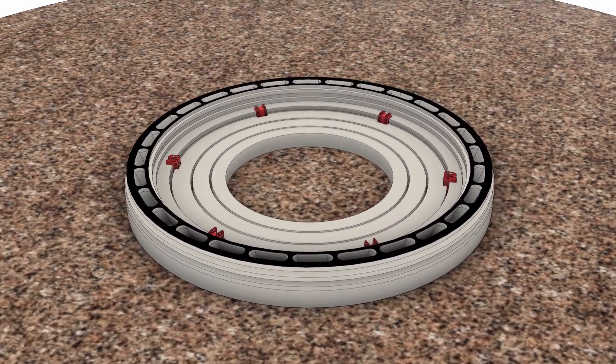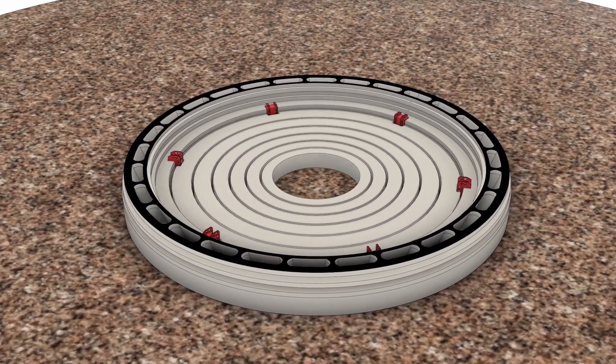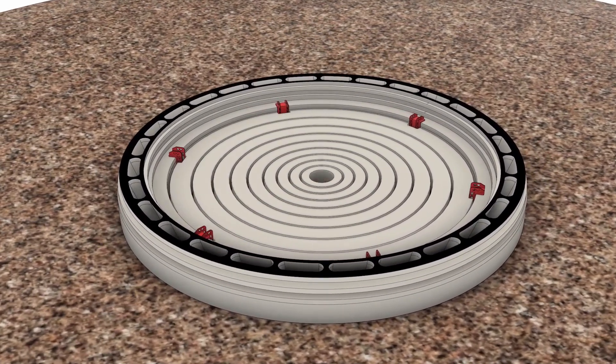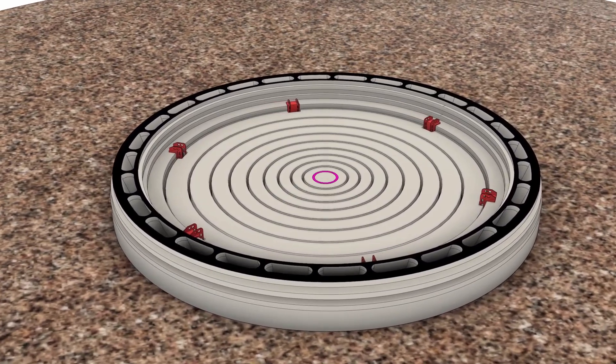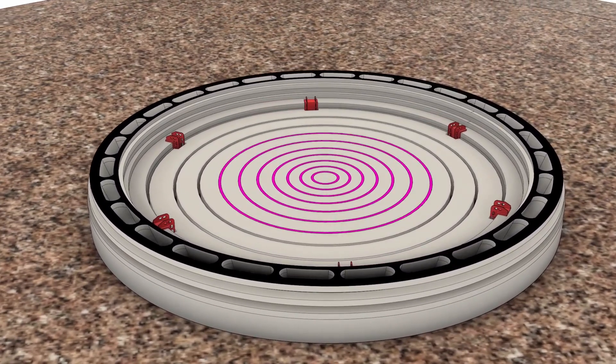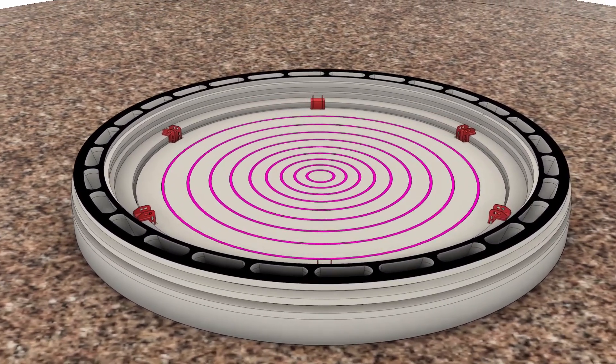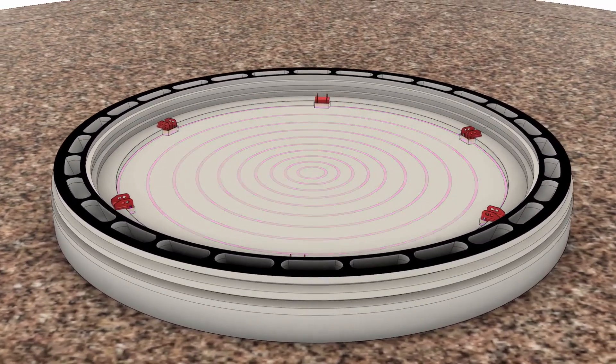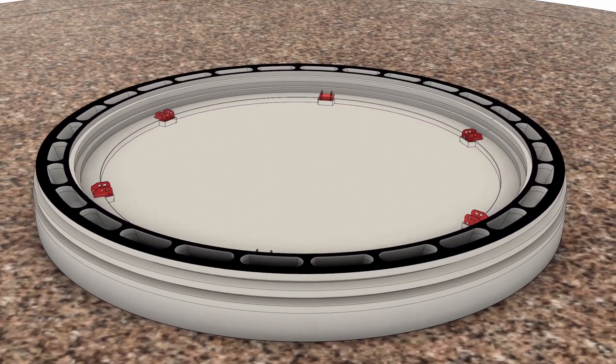In contrast to full-area plates, rings would shrink predominantly in-plane, leaving predictable joints that can be backfilled without inducing shrinkage in the overall slab. With the anchors in place, a topping slab can be printed as a final seal without the risk of geometric distortion.